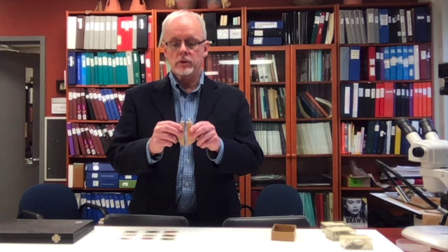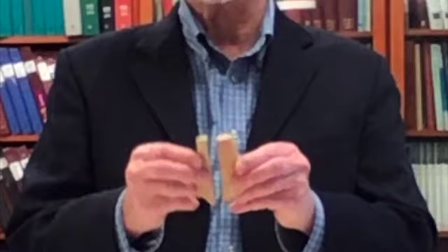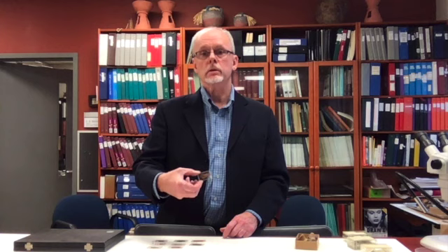We slice it once, and then we slice it again so that we get a thin kind of slab of the pottery separated from the vessel, so there's a gap here where one of those has been removed. Then we mount it on a glass slide and then polish it down until it's only 30 microns thick. That allows us to mount it on a microscope and have light actually go right through the slide so that we can see what kind of minerals and other kinds of things that there might be in that section.